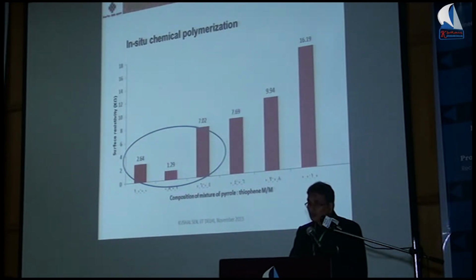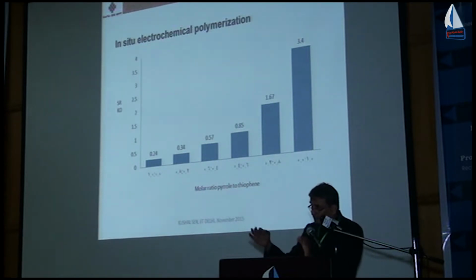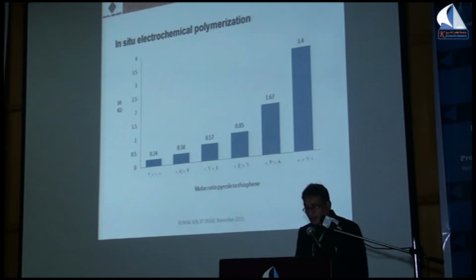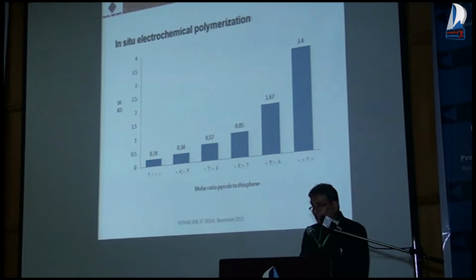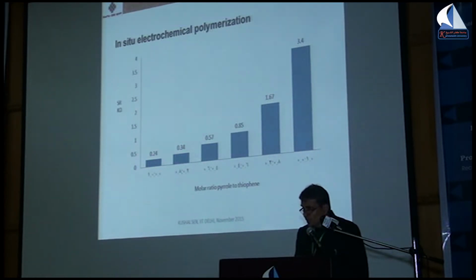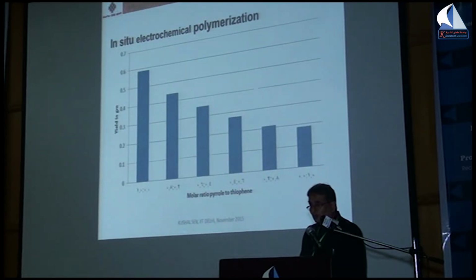But that was interesting. In a similar experiment, an electrochemical polymerization in a cell, which we call a polymerization cell, we saw the same thing: the resistivity increases. That is, if pyrrole is less, then the resistivity keeps changing and increases. If pyrrole is more, the resistivity is less. That means more conducting material can be produced. Then we measured the material obtained, in grams, how much polymer was actually produced and deposited. That also very clearly decreases as the thiophene component increases. So we wanted to understand why this happens.